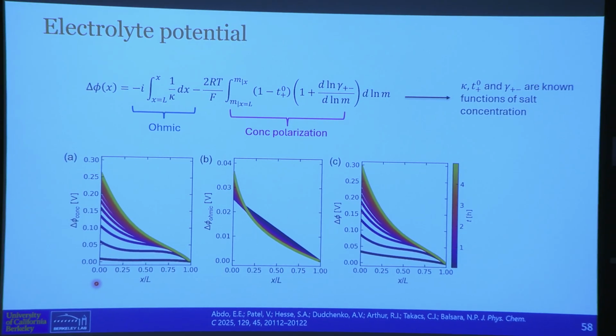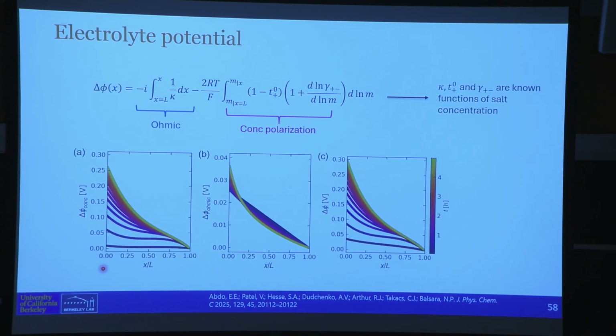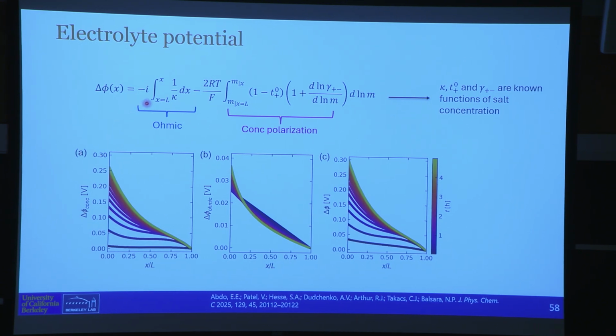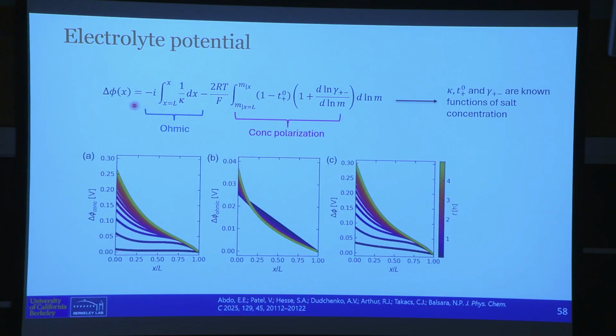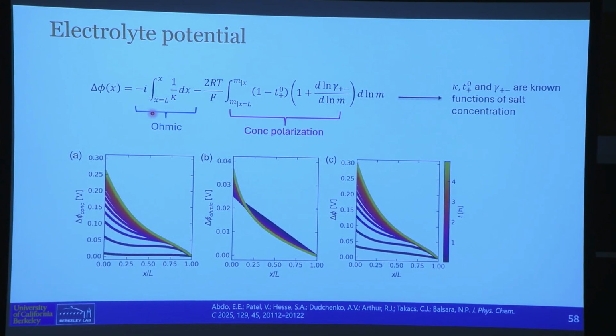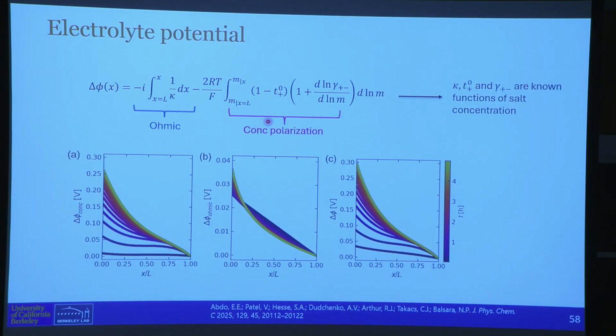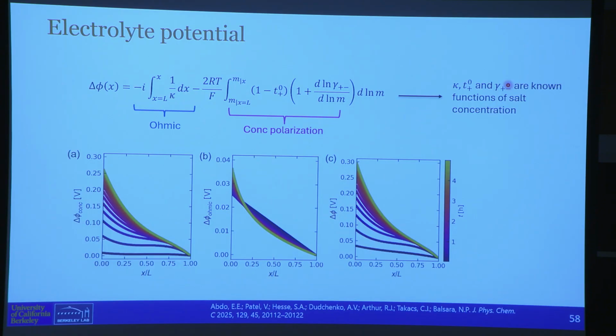And here again, Emily, this is a little bit, you need to know Newman to actually get to these equations. But Emily derived this equation. If you have a current flowing through this electrolyte, the potential drop has two components, an ohmic component and a concentration polarization component. So if you know kappa, conductivity, transference number, and gamma plus minus is the activity coefficient, and I haven't belabored this, we know all these as a function of concentration. If you know these as a function of concentration, you can back out the potential without taking a look at your potentiostat. And you know the potential everywhere.